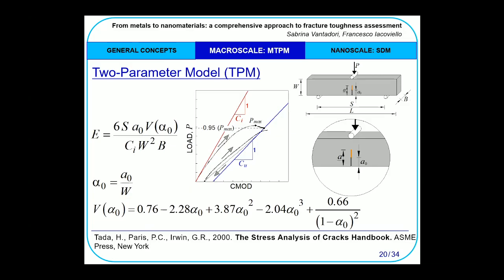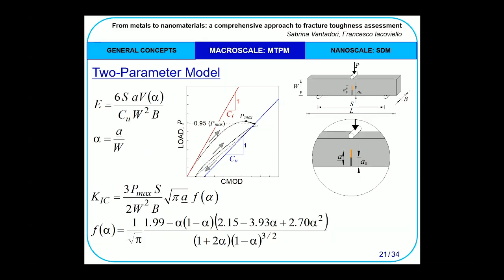The elastic modulus, according to Tada et al., is computed by exploiting the specimen geometry and the measured initial compliance Ci. Assuming a crack propagation under pure mode 1 loading, the effective critical crack length a underline is computed from the measured unloading compliance Cu, while the fracture toughness is obtained from the maximum load Pmax and the function here reported. But what happens when the crack propagation is under mixed mode loading?